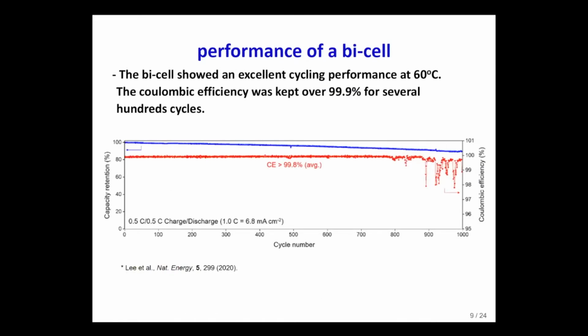We could cycle this bicell more than 1,000 times. Although it showed a signal suggesting some microshort circuits in the end, the coulombic efficiency was maintained over 99.9% until about 800 cycles.